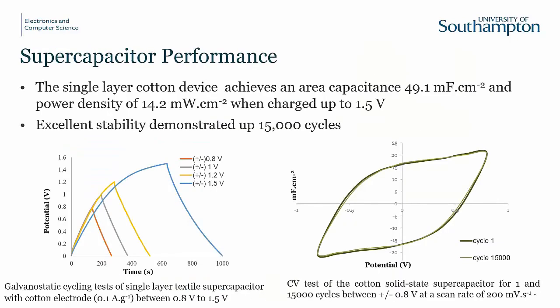It has an areal capacitance of 49 millifarads per centimetre squared. And the cyclical efficiency is excellent as well. This just shows a CV plot after one cycle and after 15,000 charge-discharge cycles. So less than 1% variation. So it behaves very, very well.